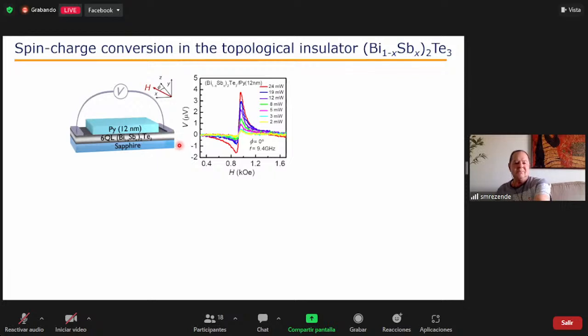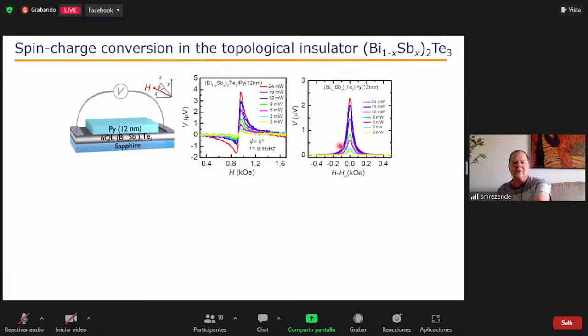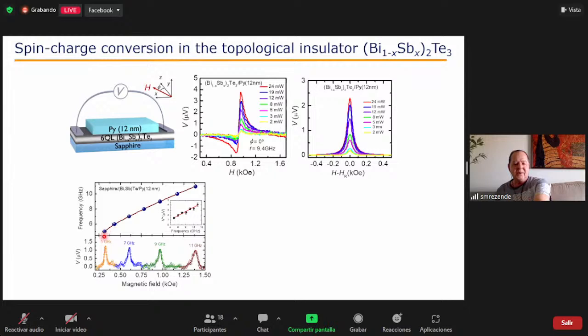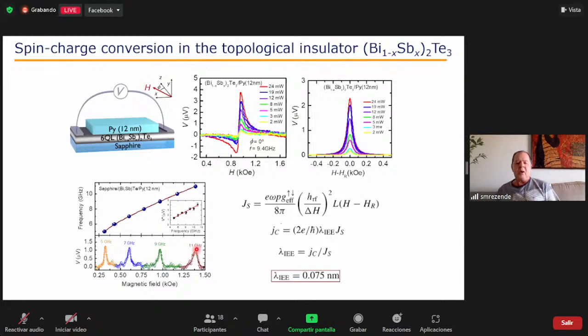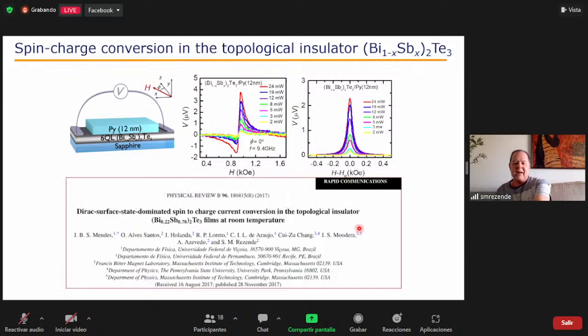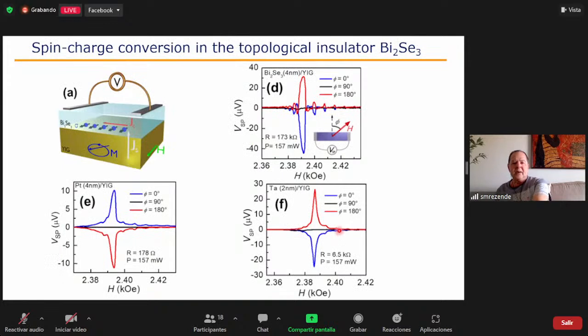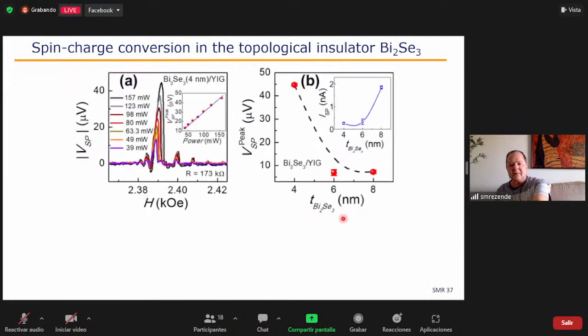And then we do spin pumping experiments and we measure the voltage, and we measure this as a function of the frequency and as a function of the intensity, and we're able to extract the Rashba-Edelstein parameter. Actually, the film was grown at MIT in the group of Moodera. Here are some more results. I will skip this.